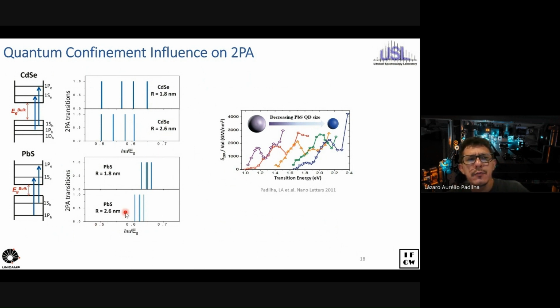And that comes from the fact that lead sulfide has a very unique type of band structure where the electron and hole effective masses are very similar, which doesn't happen for cadmium selenide. And furthermore, the bulk band gap is pretty tiny compared to the confinement energy, which is the opposite of what you see for cadmium selenide.